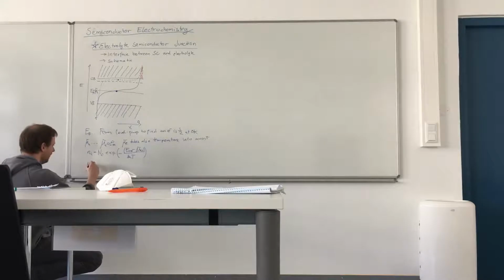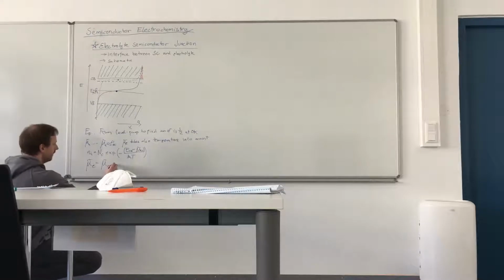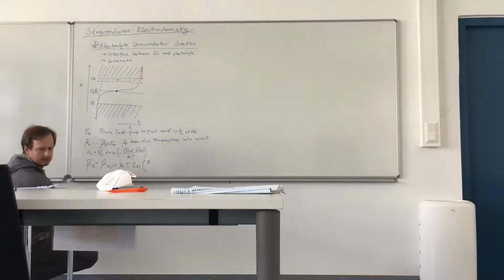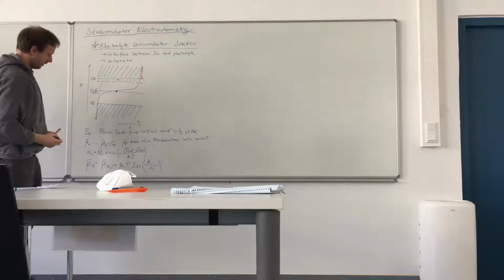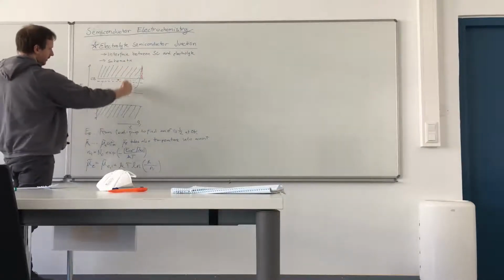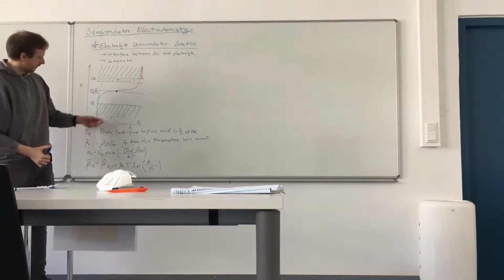Hopefully you see it. So mu tilde E, for the doped case, is related to mu tilde E I for the intrinsic case, if one has not inserted these states in the semiconductor, plus kT ln of n divided by n_i.